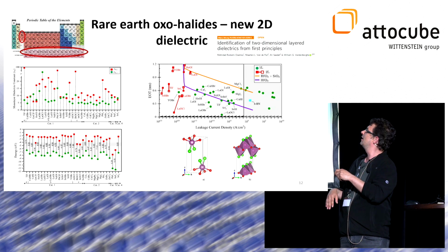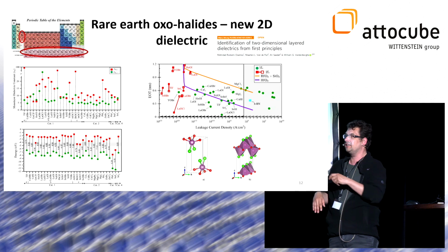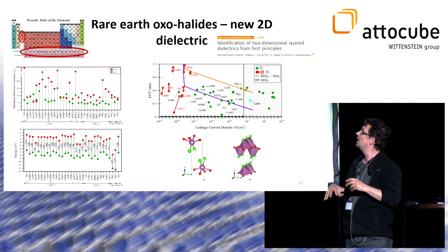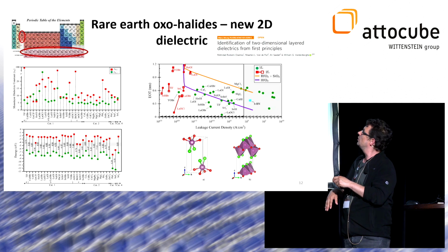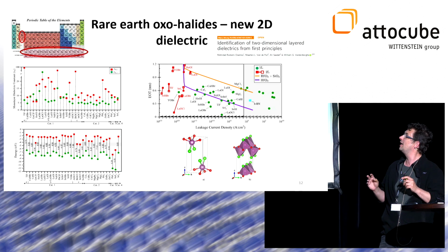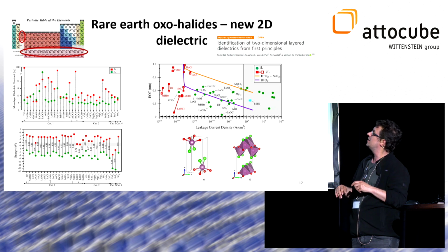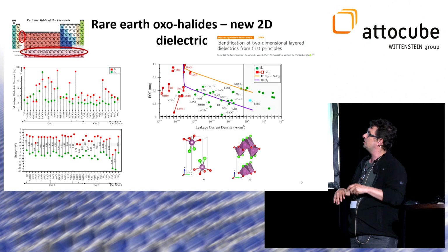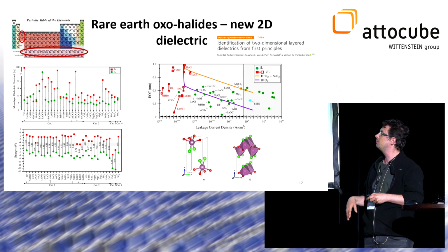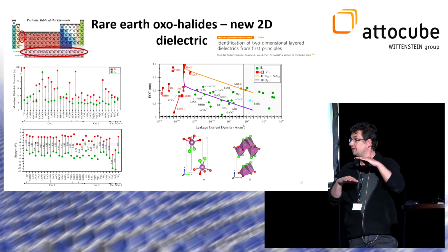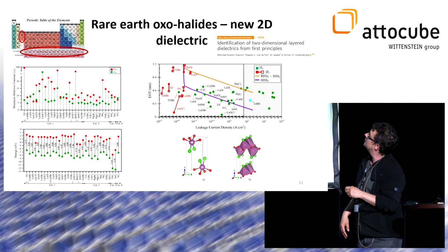You have hydride halogenides, which are possible to synthesize, but their stability is extremely limited, and by moisture and oxygen they decompose in seconds. Then you have a lot of interesting halides like calcium iodide, magnesium iodide, but they are extremely moisture sensitive. But you also have this compound which adopts the matlockite structure, lead chloride fluoride, which is a compound known for many hundred years, but due to strong interlayer interaction, it's very difficult to get this PbClF exfoliated.